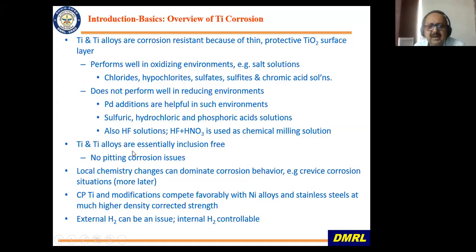The other point about titanium alloys is that there are no inclusions in titanium alloys because they are melted in vacuum, very pure materials. So it is unlike steel. So absolutely clean. So there is no pitting corrosion taking place. But titanium alloys do undergo crevice corrosion because of the nature of this oxide. And hydrogen also can cause problems because hydrogen is very much soluble in most of the titanium alloys, and it can cause embrittlement problems. So you have to be careful.